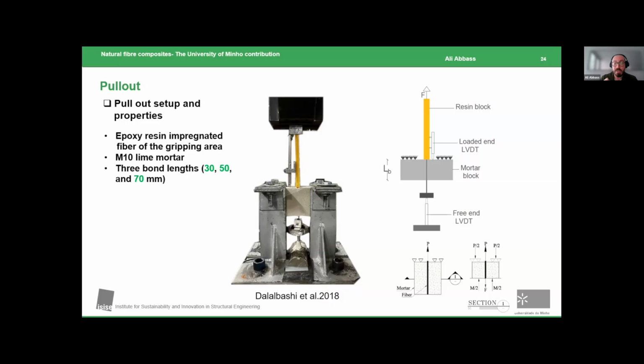It was developed by our colleague, Ali Dalalbashi, who has done a great job with it. Here the boundary conditions are applied on the upper part of the mortars in a manner called pull-push, so that we do not grip the mortar, we do not transfer any load to the interface, and we cannot manipulate the results. So here we have the bond behavior fully dominating the deformation. We used two LVDTs, one at the loaded end where the friction onsets, and one at the free end to establish when the friction state throughout the bond length was achieved.